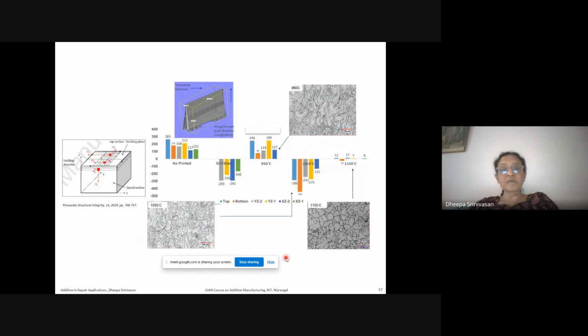Okay, so experimentally determine the residual stress along and perpendicular to the build direction through X-ray diffraction. Then establish correlation of residual stress in the coupon with necessary build parameter optimization. Then perform the transient thermomechanical finite element analysis, numerical modeling, and then correlate the residual stress experimental measurements with the numerical simulations, in such a way that you optimize the parameters. So that is the recipe highlighted in these four boxes. So with that, that is what we did.